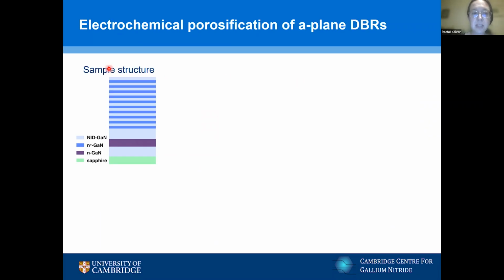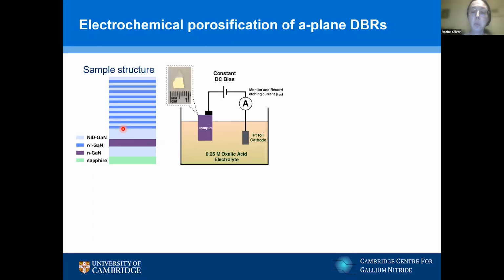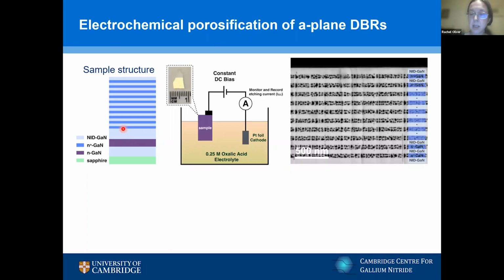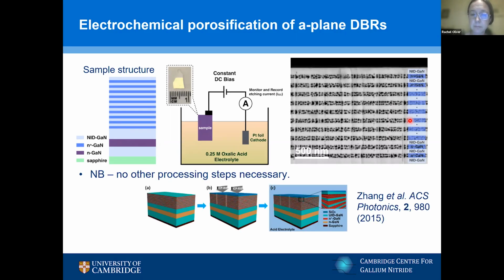So we're doing this for DBRs, which means we need an alternating high and low refractive index structure, which starts off as an alternating highly doped, undoped structure. We apply our electrochemical technique and we make something like this. This is an A-plane distributed Bragg reflector with layers of doped and of porous and non-porous material.